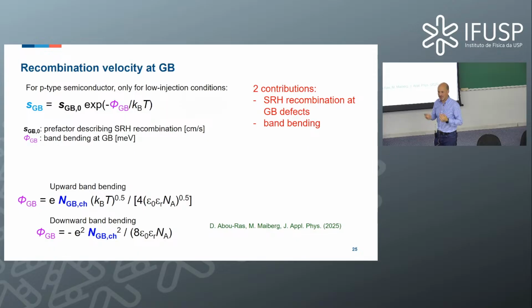This has never been dealt with, really, because it's a quite nasty derivation, I can tell you. It's not so nice. This one is a 4 or 5 liner, very easy, yes? You can find it in many, many publications. And the interesting thing is that when you derive this equation, you see that by the derivation itself, this magnitude is limited. It means that the barrier heights are maximum several tenths of millielectron volts, either upward or downward. So it's a very small perturbation of the conduction or valence band edges. Yes, very small. This means also that the current is not very affected, so the transport of charge carriers is not affected.